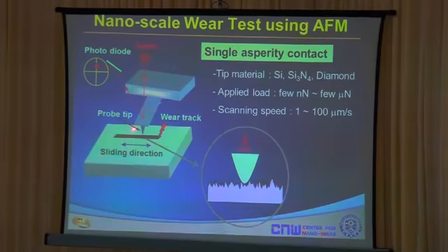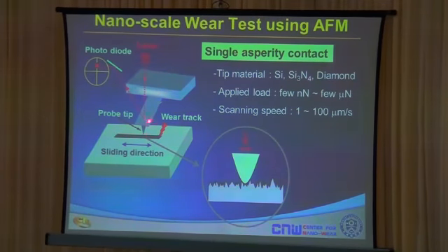Atomic force microscopy is based on a very sharp tip that scans over a surface, and the deflection of this cantilever is measured using very sensitive laser interferometry. By noting the amount of deflection, we can map the surface. And if you scan this in the X direction and Y direction, you're able to map the surface topography in 3 dimensions. And we can buy this equipment commercially, as you all know.